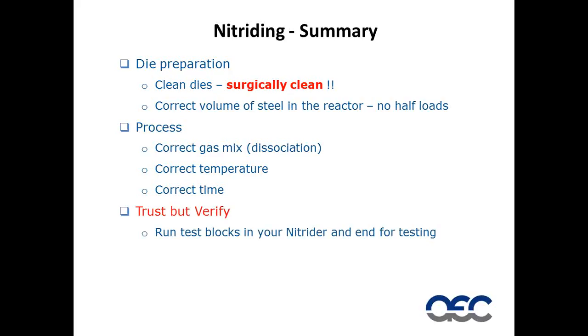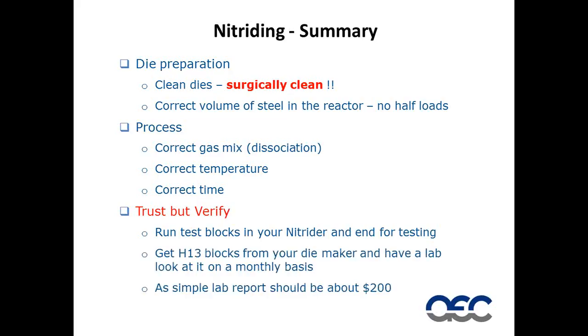What I believe is that at least once a month, probably more frequently, you should run a test block in your nitrider and send it for testing. Sorry, there's an S missing there. That should be send for testing, not end for testing. What you do is you contact your die maker and say, please give me a piece of H13 about 1 inch by 1 inch by half an inch, and you put it in with the dies. It gets nitrided and you send it to a lab.